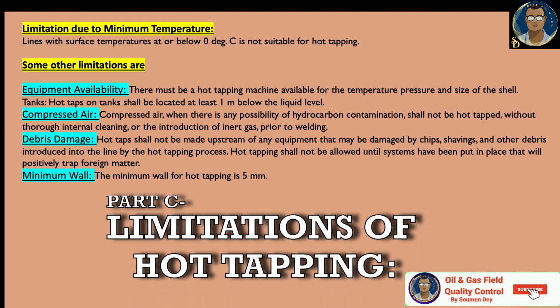Debris damage. Hot taps shall not be made upstream of any equipment that may be damaged by chips, shavings and other debris introduced into the line by the hot tapping process. Hot tapping shall not be allowed until a system has been put in place that will positively trap the foreign matter. Means the cutting bars or anything shall not fall into the pipeline. So we need to arrange something to trap the foreign metal.